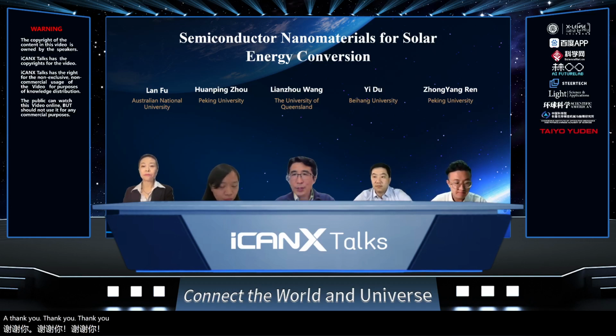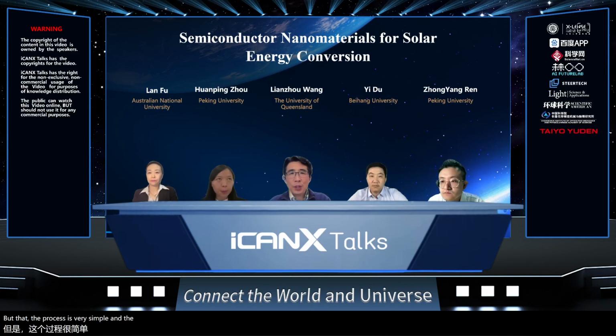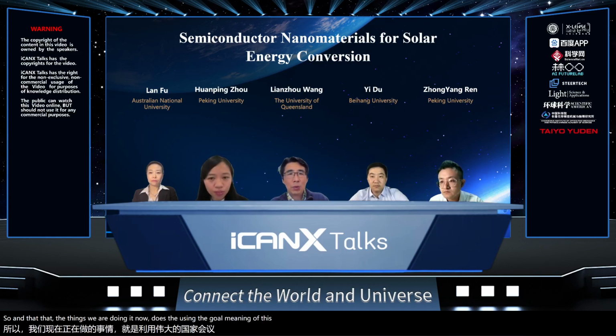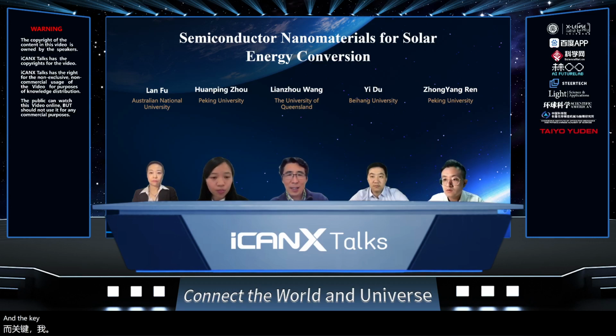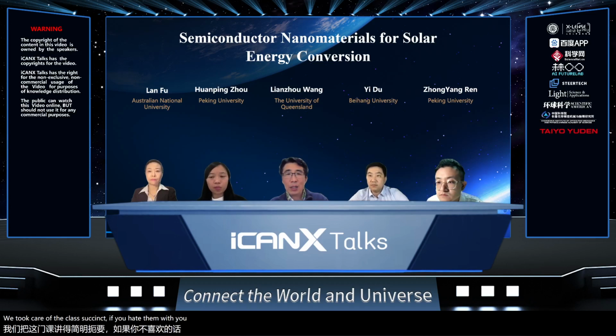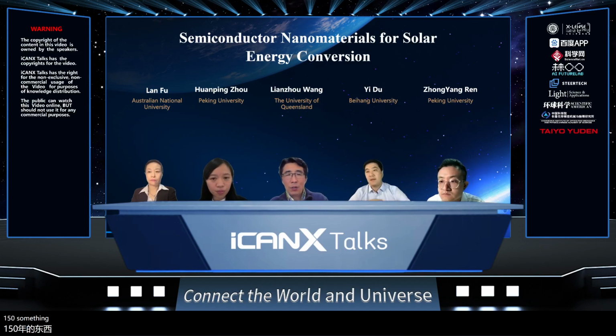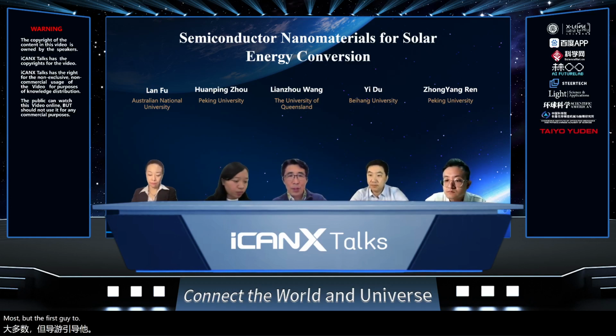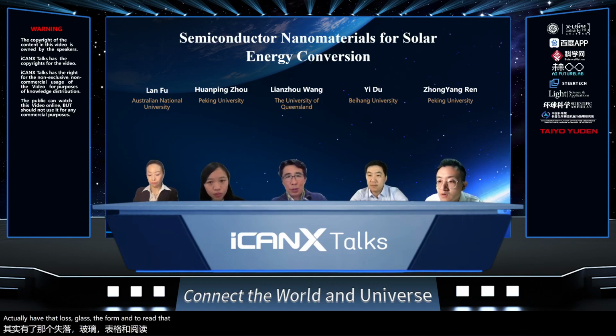Thank you, Zhongyang. I would say that the process is very simple, and the perovskite itself can have actually a very diverse composition. I think Professor Zhou knows this. So what we are doing is just using the ball milling process to produce the composite, basically mixing them together. The key idea here is to choose the MOF material, which can have the glass function. That means if you heat the material at a certain temperature, 200 or 250 something, it does not damage the perovskite material, but also can help the MOF glass to form and to wrap, that means to coat the perovskite surface. I think that's the key idea.